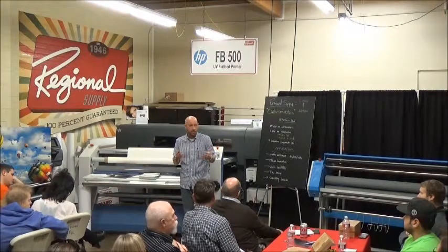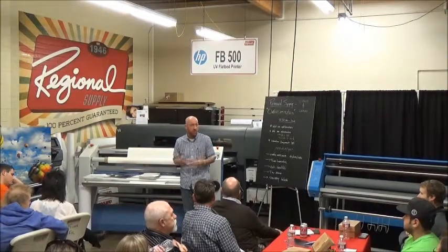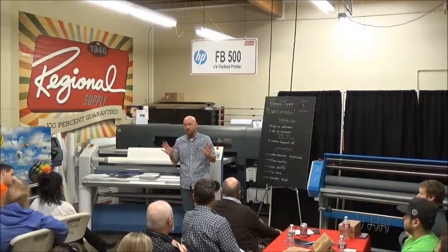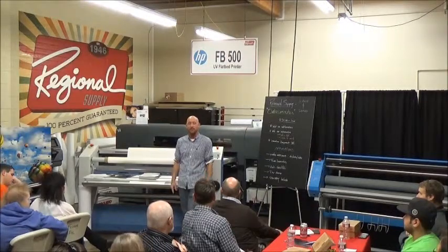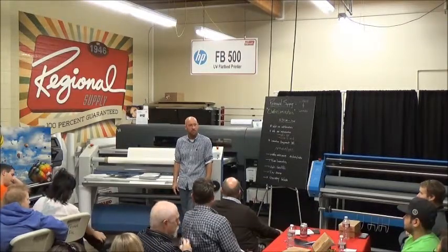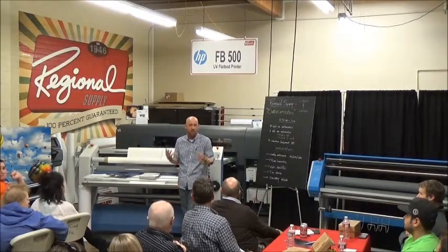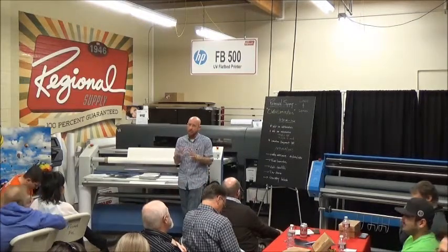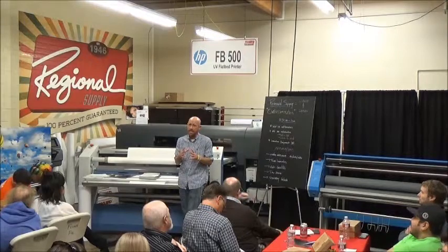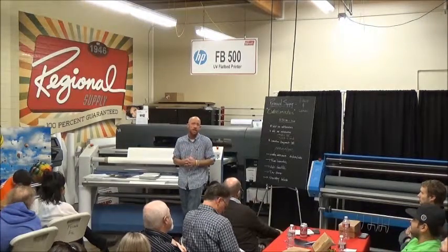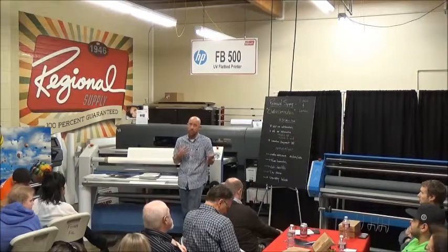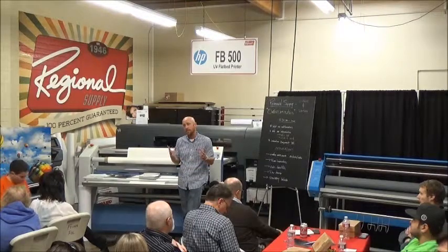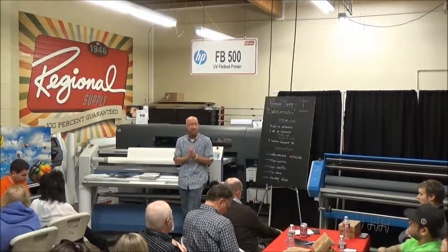With any kind of solvent-type printer that you're using, I know this is a gray area, so I'm just going to tell you what we're told, and then we'll leave it at that. Typically, what is suggested is 24 hours for the product to outgas those solvents, so that when you laminate the product, you're not encapsulating those solvents or trapping them inside the print on that layer of ink, which can cause problems in both directions. It can go backwards and attack the adhesive, and in some cases it'll go forward and attack the adhesion between the laminate and the vinyl itself.